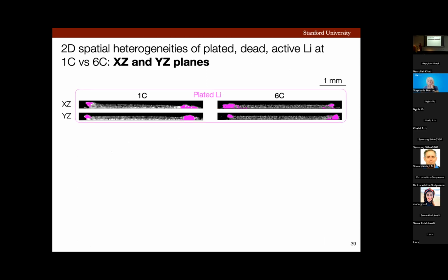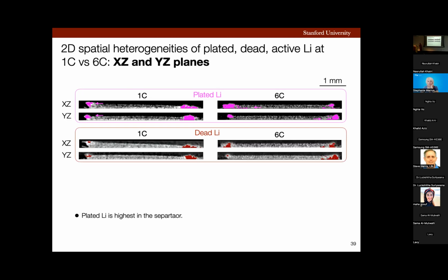If you look at this data, you would notice that lithium is plating mostly on the edges of the graphite anode at both the charging rates. This is a similarity. But you would also notice that this plated lithium is mostly present in high amounts in the separator or near the interface, as compared to near the current collector. Now, if we compare these images with those of dead lithium, you would notice that not all the plated lithium became dead. For example, let's focus on this blob in the cross-sectional XZ image at 1C and compare that to the blob of plated lithium. This is much bigger than this, which means most of the lithium near the current collector went back to the cathode during the discharge process. However, mostly lithium at the interface and in the separator is the one that became dead.